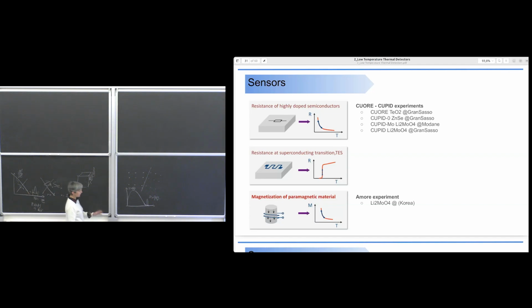And most experiments with not very good energy resolution, to be polite, are working on isotopes for which the half-life is very long. The half-life of molybdenum-100, the isotope that we want to use in CUPID, is quite short. It's something like 10 to the 18 years. But still we have such a high energy resolution, that means 5 keV or 10 keV, it's the same, that we are not worried by this background, which is orders of magnitude lower than the background from external radioactivity.